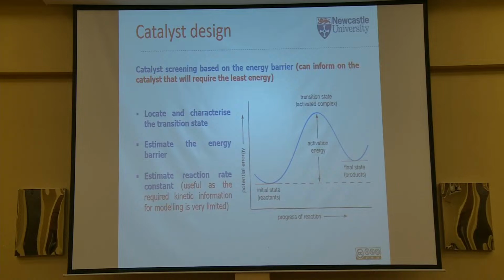So what the method that we are using at the moment does is to estimate the transition state associated with a specific catalyst in this process. So the transition state looks like this for non-chemical engineers, and with the transition state we'll be able to estimate the activation energy. All right, so if we can do that for different catalysts, we can then use that as a basis to compare which one is acceptable or not.